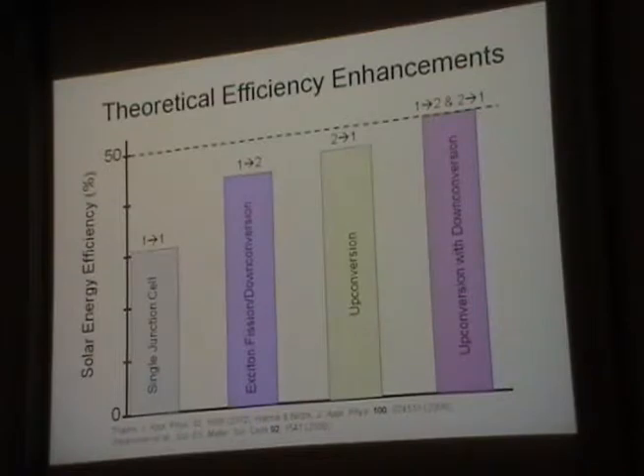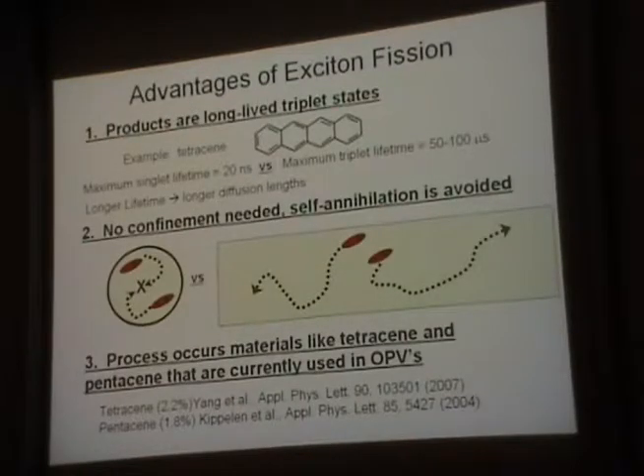This is all theoretical. But the point here is that these proportional gains, this 33% gain, should be applicable to any solar cell. So if you want to use amorphous silicon or something like that, if you can more efficiently harvest the photons, you should get that 30% gain in efficiency. So 10% to 13% or 30% to 40%. That type of gain should be general, no matter what your base efficiency is. Okay? You don't need the perfect silicon cell to have this work. So it should be a general strategy to raise solar cell efficiencies, no matter what the solar cell.